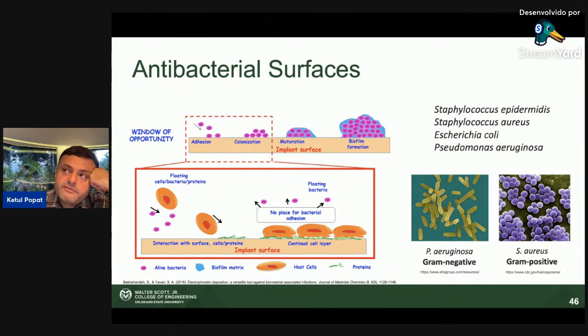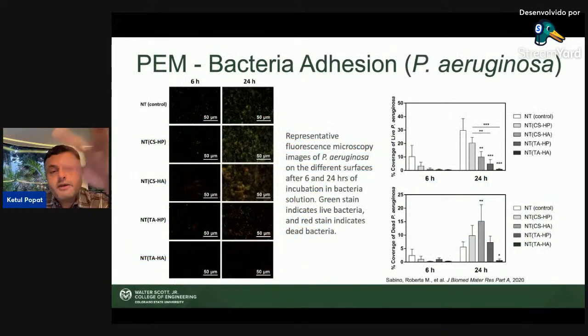So we wanted to see specifically if we can reduce the adhesion of gram-negative bacteria. And so we have done some work with both polyelectrolyte multilayers as well as superhydrophobic surface. Polyelectrolyte multilayers again were very good because we know that tannic acid has antibacterial properties. What we found out was that with tannic acid heparin and tannic acid hyaluron.